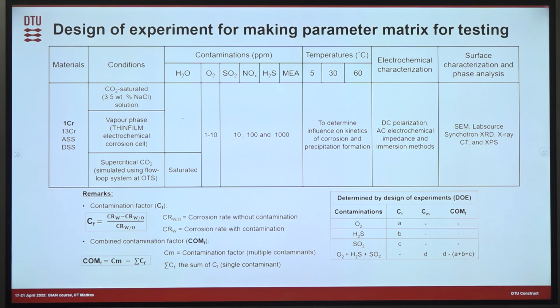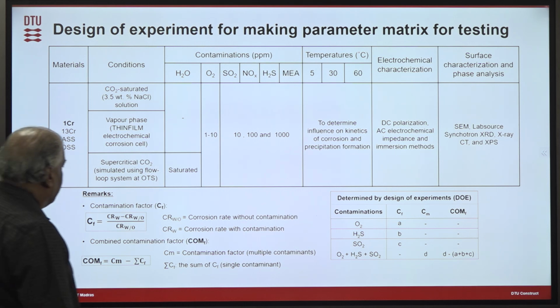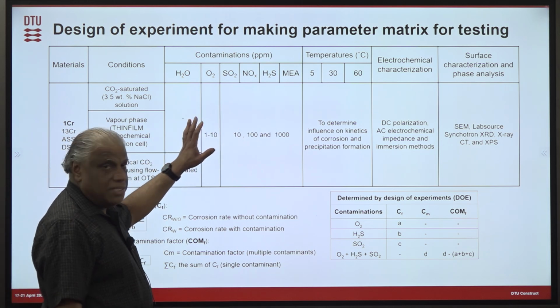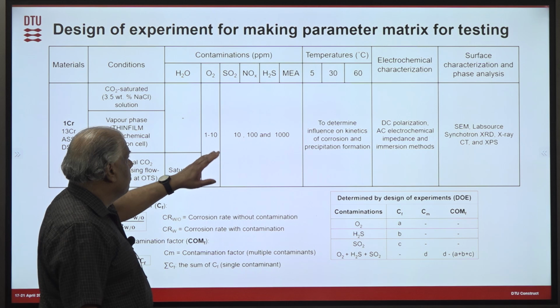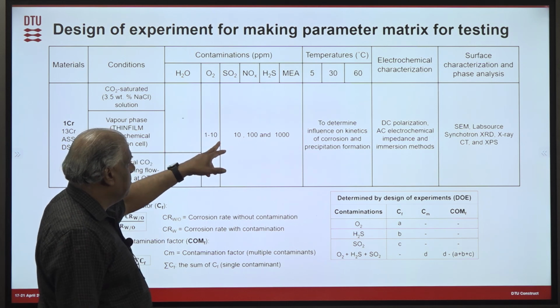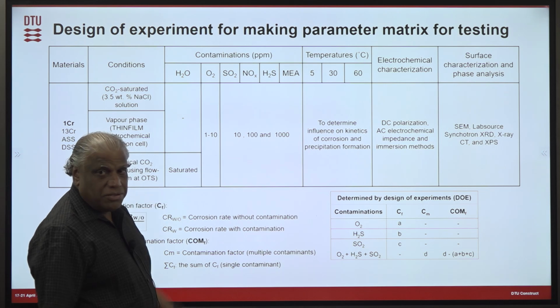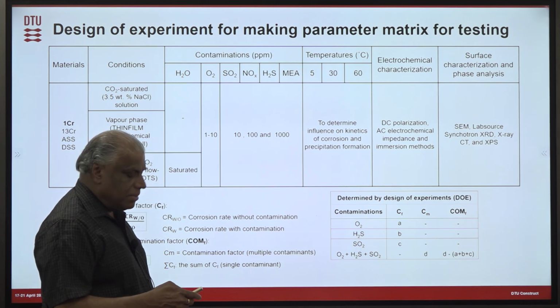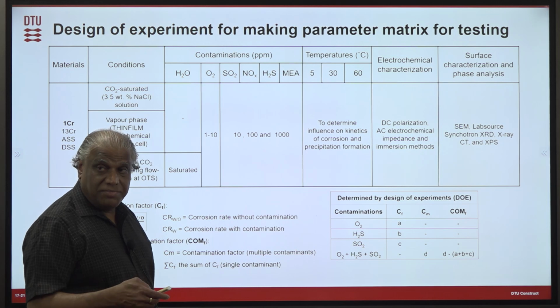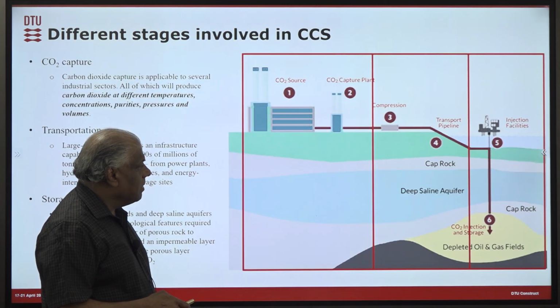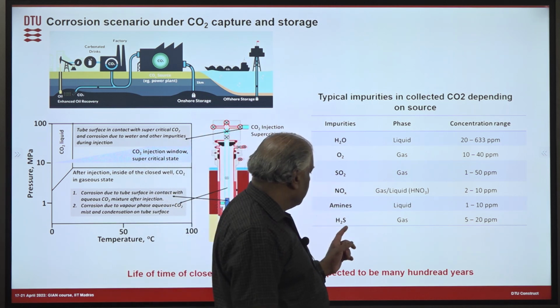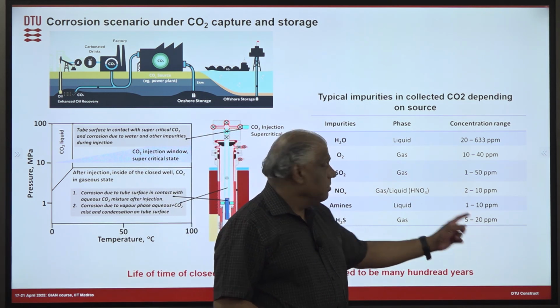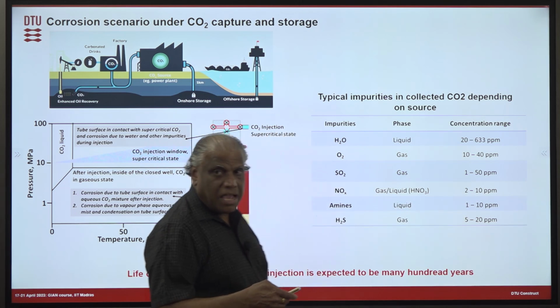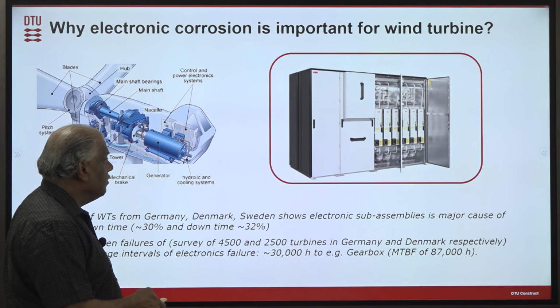So what we try to do is, since we have a lot of impurities, we do a design of experiment to see what range of composition we really need to take. So we study oxygen at 1 to 10 ppm and all other things from 10 to 1000 ppm, at lab scale. And why do we do 1000 ppm? Because you can see that here H2S is only 20 ppm and SO2 is only 50 ppm, but in the lab scale experiment we study with